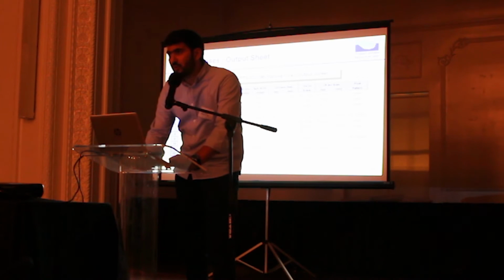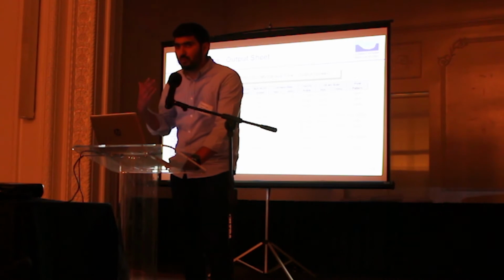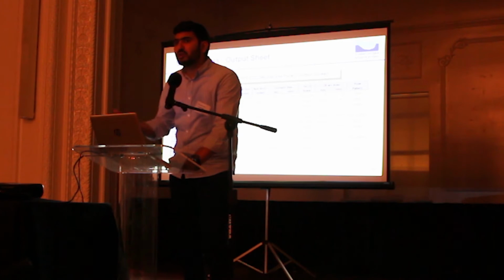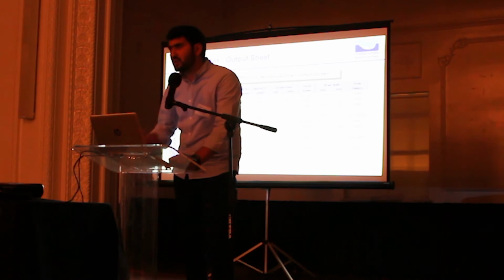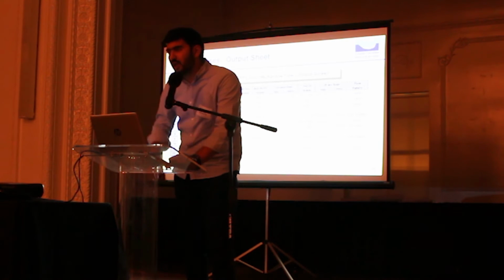Then we have the pH. So the pH is calculated for us. And as I mentioned earlier, the value of the pH depends on the partial pressure of CO2 gas and the concentration of bicarbonate. So for the very last case, where we have bicarbonate initially added, I have a pH value higher than the other cases where the bicarbonate was not added into the system.